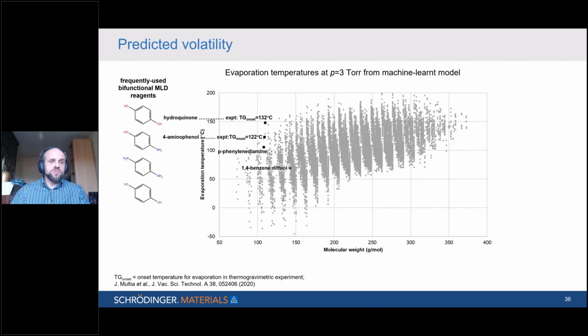We look at the next one, 4-aminophenol, which has an onset temperature of 122 degrees C, and we're predicting around 125, so very close. Certainly the trend is correct. Paraphenylene diamine with 2 amine substituents or functional groups is more volatile, down around 100 degrees C, and 1,4-benzene dithiol with 2 SH groups is more volatile again.